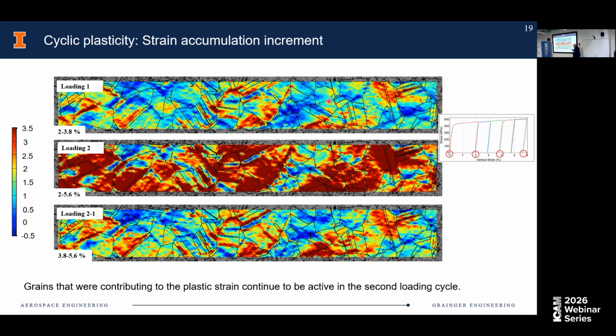So essentially what we see is that plastic deformation just keeps accumulating at the same places, which are in some sense determined from the very beginning, just by the microstructure itself, really, right? That's kind of how this came about. Can we just use the microstructure to determine what will happen in the future, since this seems to be, at least at the mesoscale, what drives the development of the strain accumulation? So plastic strain just continues to pile up at the same place.